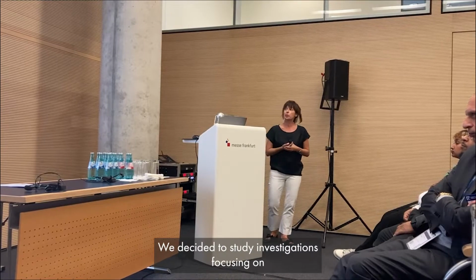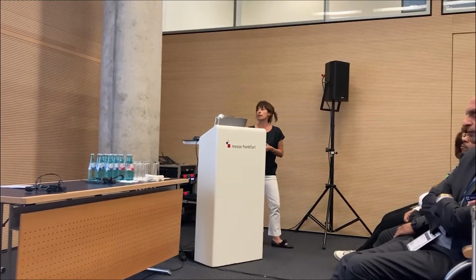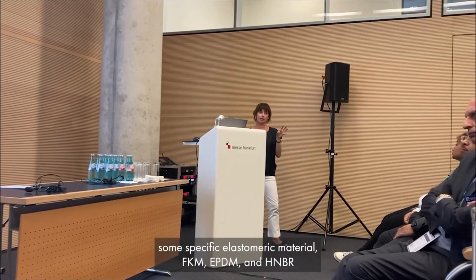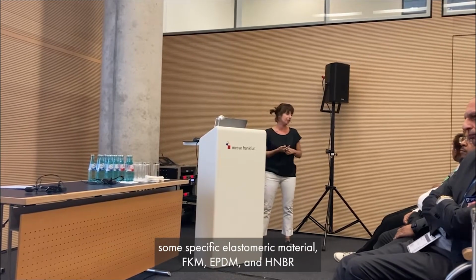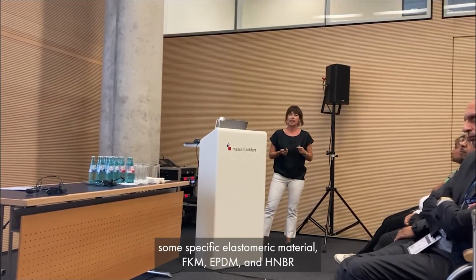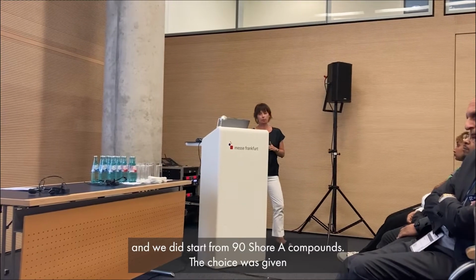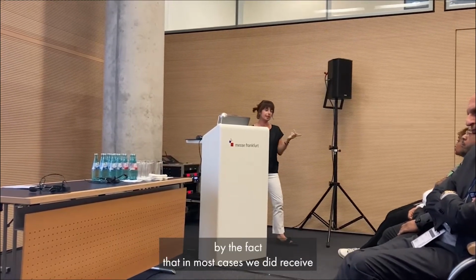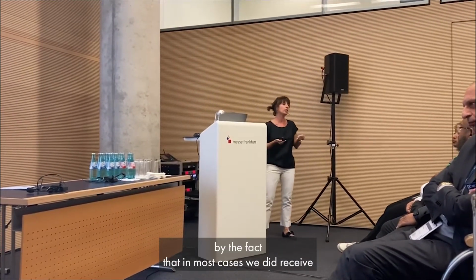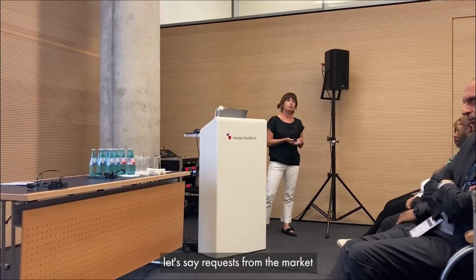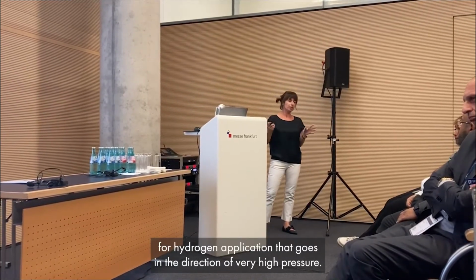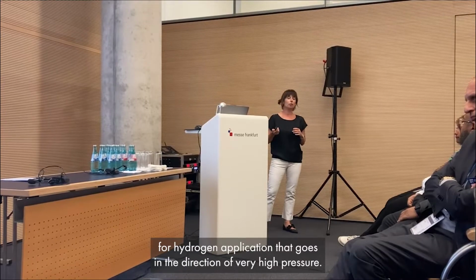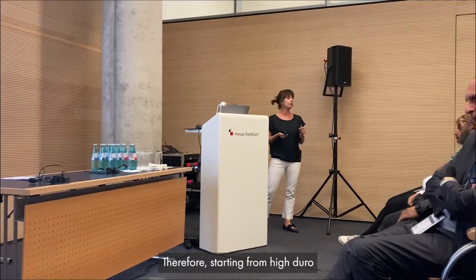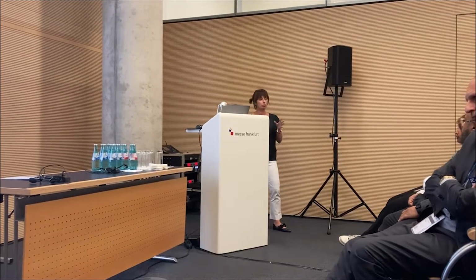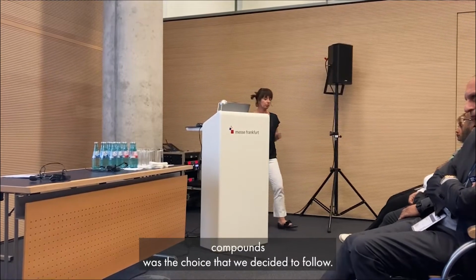We decided to start the investigation focusing on some specific elastomeric materials: FKMs, EPDM, and HNBR. And we did start from 90 Shore compounds. The choice was given by the fact that in most cases we did receive requests from the market for hydrogen applications that go in the direction of very high pressure. Therefore, starting from hard compounds was the choice that we decided to follow.